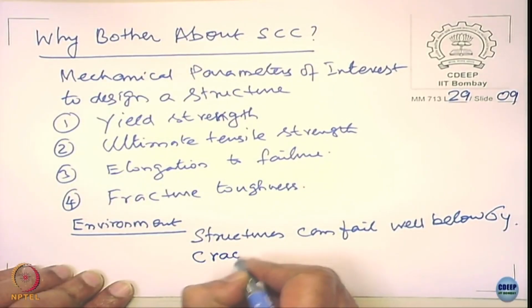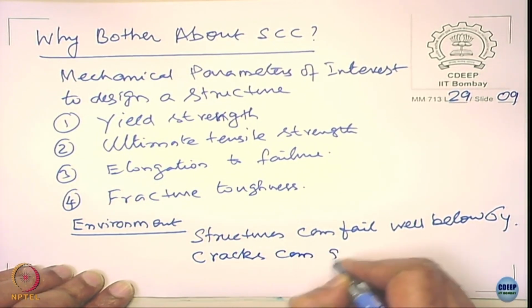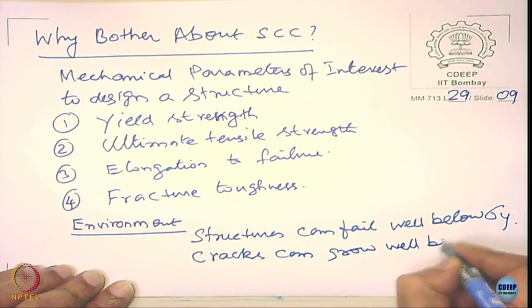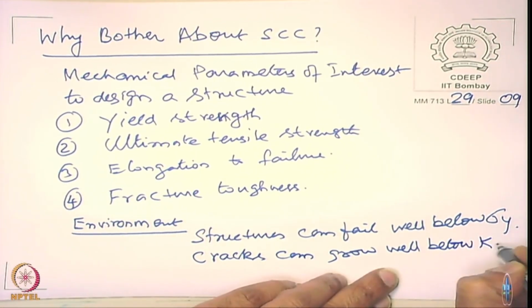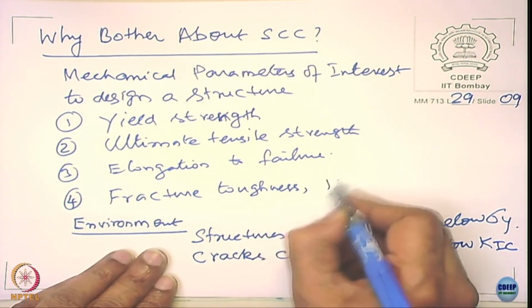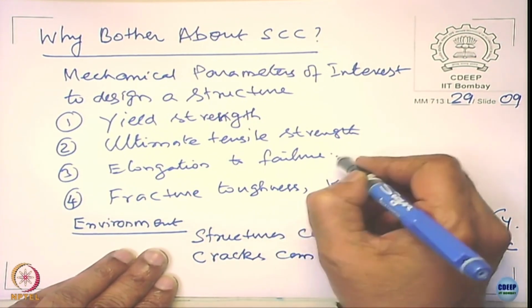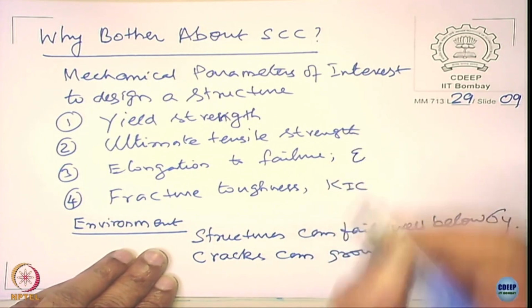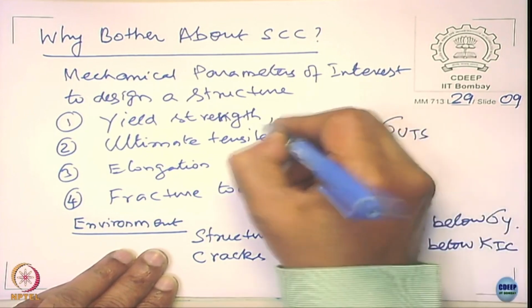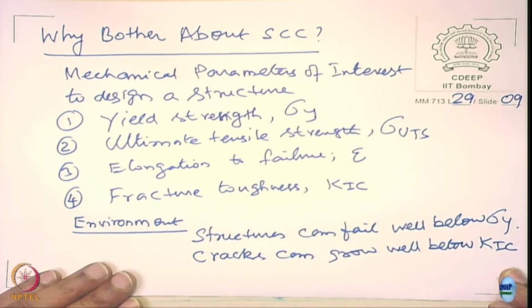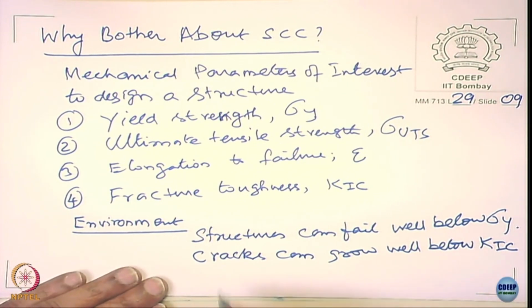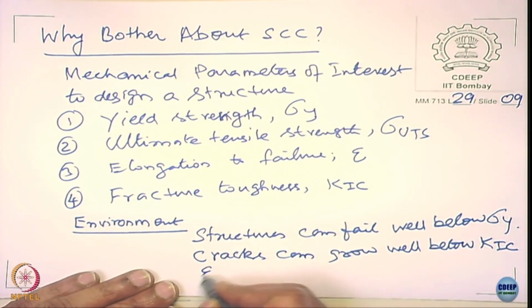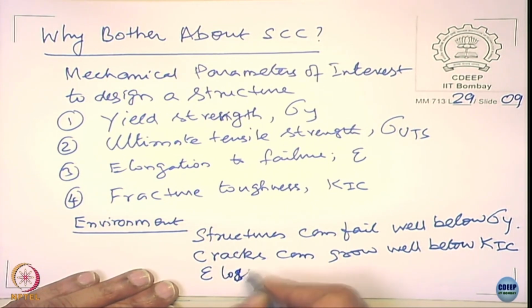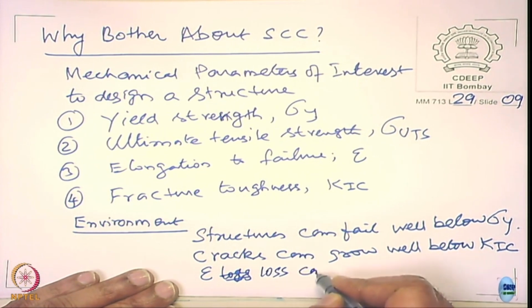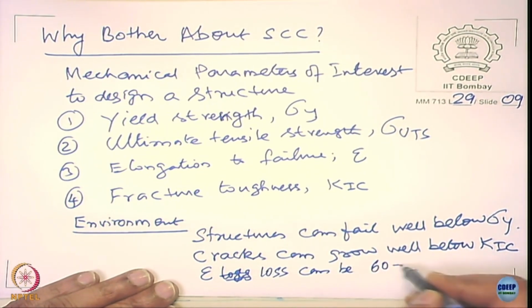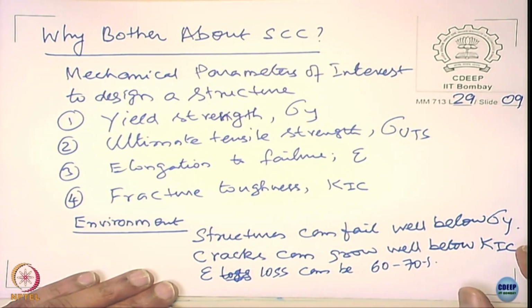cracks can grow well below K1C, fracture toughness. K1C, right, elongation is given as epsilon, sigma UTS and sigma yield strength. That is because the elongation loss can be 60 to 70%. I can lose my elongation 60 to 70%.